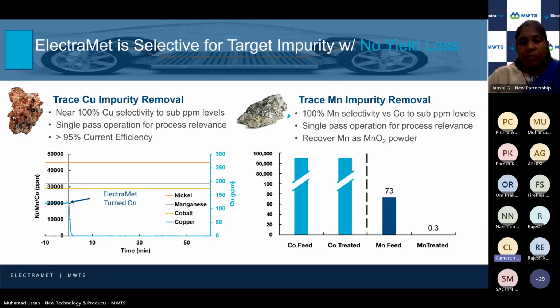Just like copper, we put this through our system, and in a single pass operation, we are converting that dissolved manganese 2+ sulfate into manganese dioxide in our cell without adding anything else back into that cobalt stream. So we don't need any pH adjustments. We just need solids to not be in there if you don't want to clog, which they don't want in there anyways because that's the product stream. So you have two very viable, highly efficient economic solutions depending on which route you want to go, from straight to cathode active material, or if you want to make the different battery salts. ElectraMet systems can integrate in each one of those processes. Next slide, please.